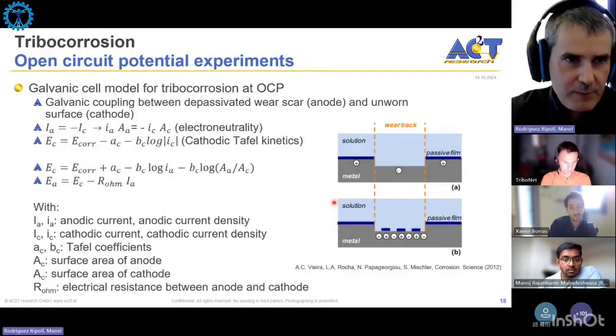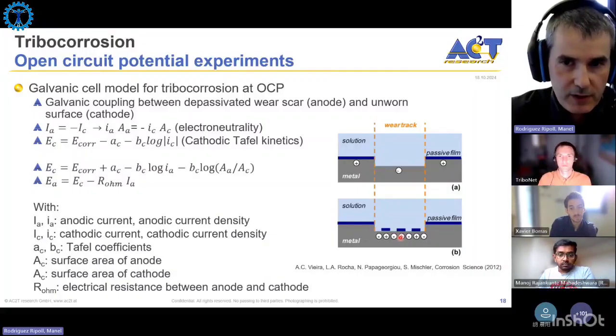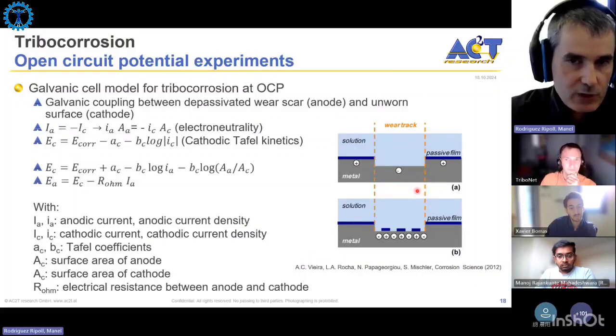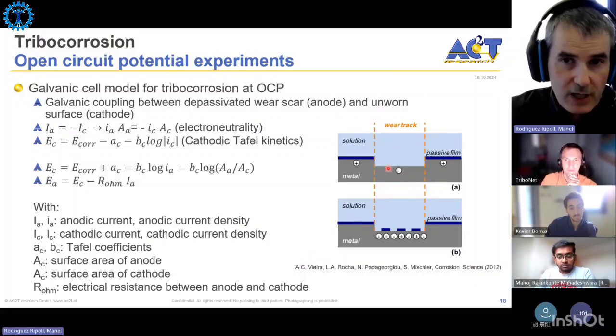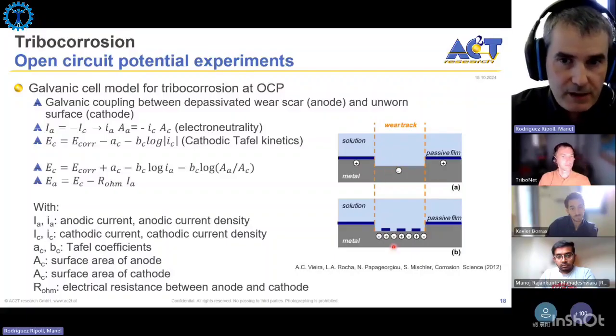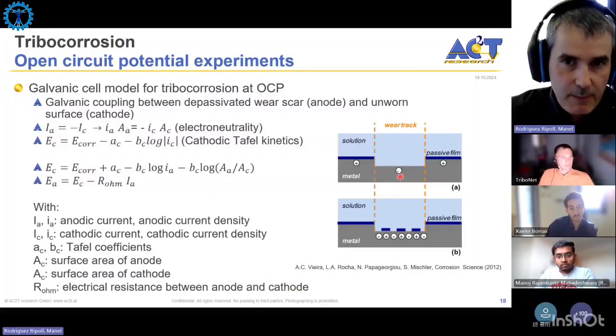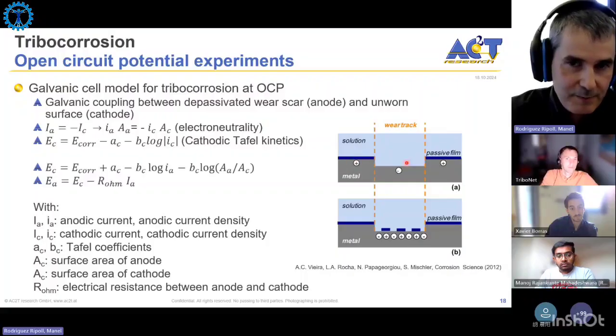And we'll maybe not go into much detail. You can also get quantitative data from open circuit potential experiments. It was proposed in a model published in Corrosion Science 12 years ago by Vieira and collaborators, and the model basically relies on what I just mentioned. You have the depassivated area that can be fully depassivated or only partly depassivated, and then you end up building a galvanic coupling between the non-passive part and the passive ones.